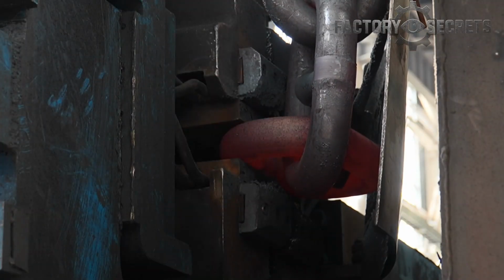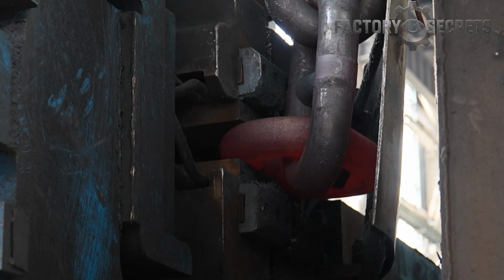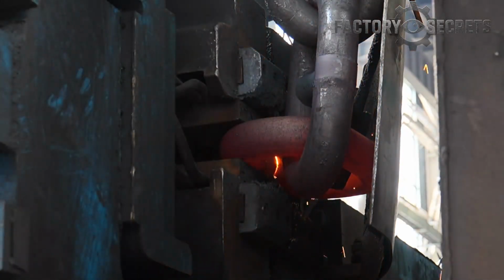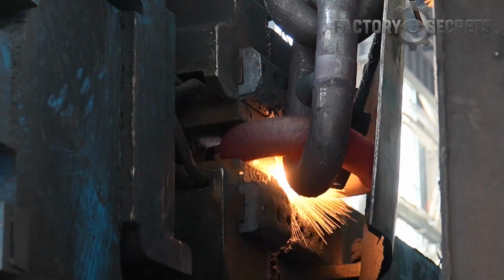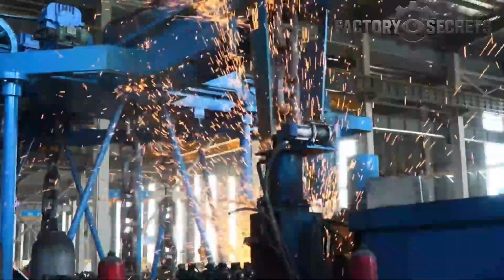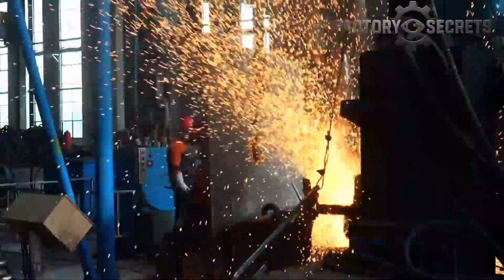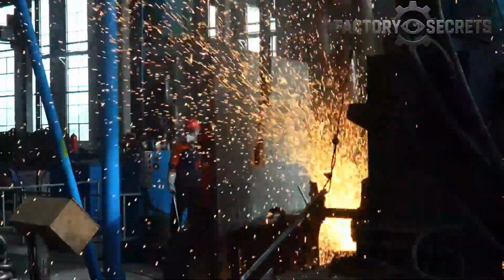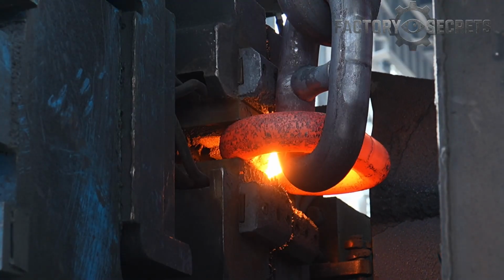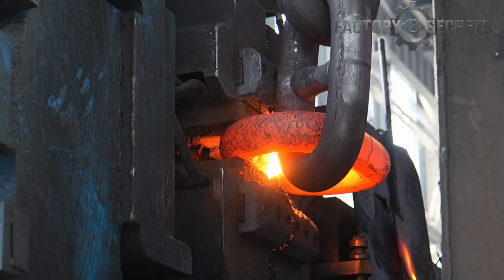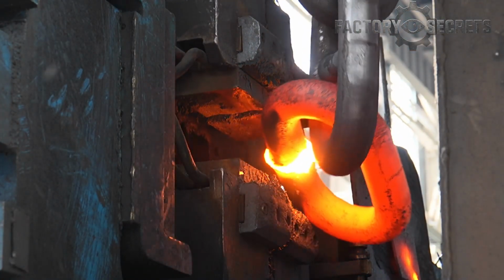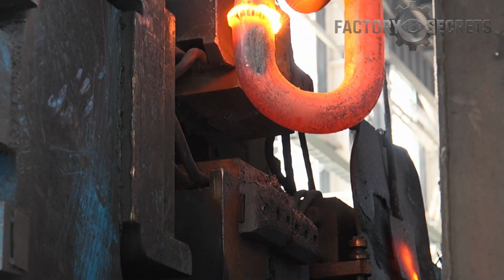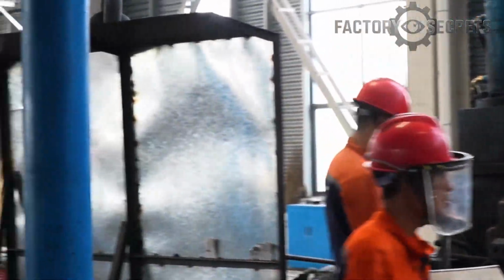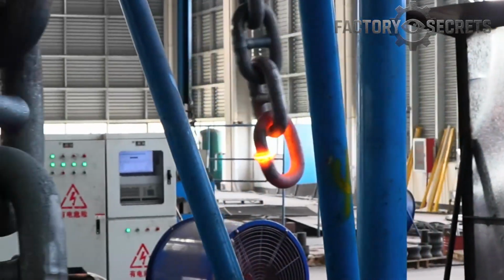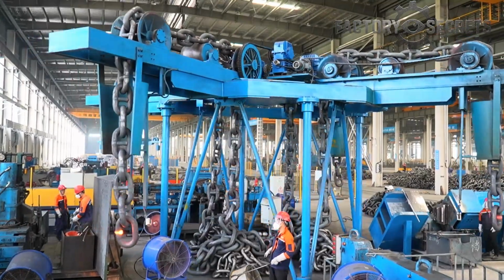Flash butt welding. The two ends are pressed together with enormous force while electrical current runs through the joint, generating intense heat right at the contact point. Sparks fly. The metal fuses at the molecular level. When the machine opens, what was two separate ends is now one seamless joint. Smooth, strong, unbreakable. But even a perfect weld leaves a seam. And in this industry, a seam is not acceptable.